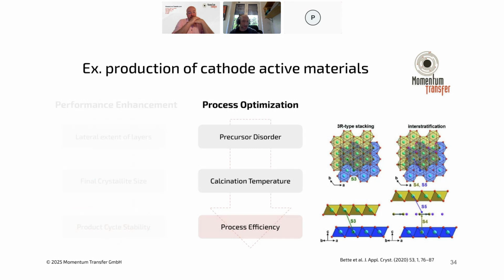And on the process optimization side, there's precursor disorder. This comes from the stacking patterns of these layers. They can have different kinds of stacking patterns that can intermix and cause stacking faults. And you can also get what's called interstratification, where you have different kinds of guest molecules that come between the layers and change the layer spacing. And you can quantify these properties, again, from X-ray diffraction. And this helps to predict the ideal temperatures to actually calcine the materials.